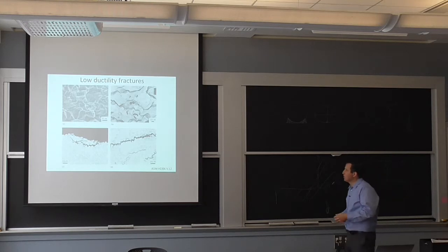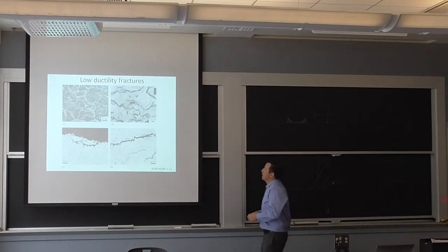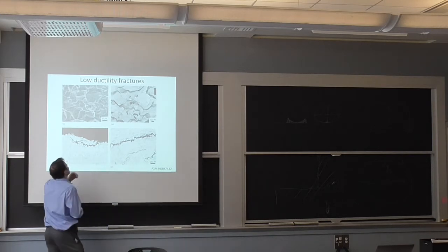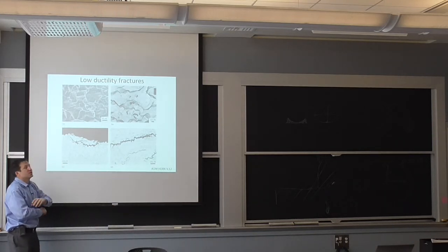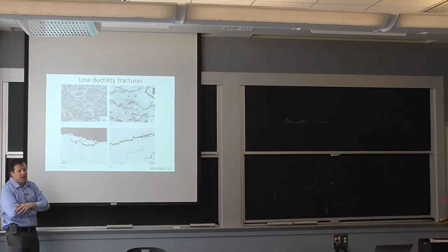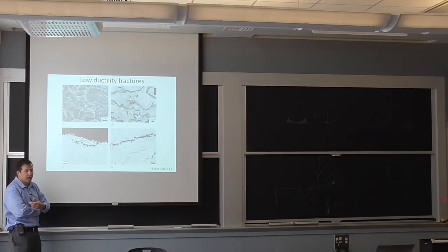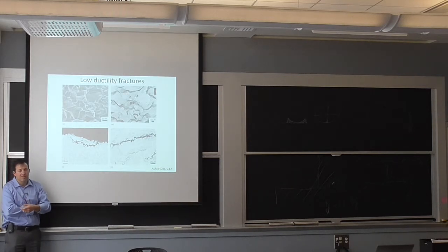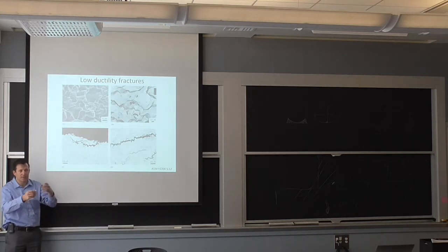What you want to avoid with the same material — on the top left we're looking at steel. Steel will show this behavior sometimes when it's very cold. What's going to happen is instead of having this plastic deformation — the movement of the dislocation — it takes time for that deformation to take place. So if you have an impact — old bridges, very old ships — you can go through historical cases where this fails. Instead of having the movement of the dislocation and the blunting of any crack you had, it starts to separate.